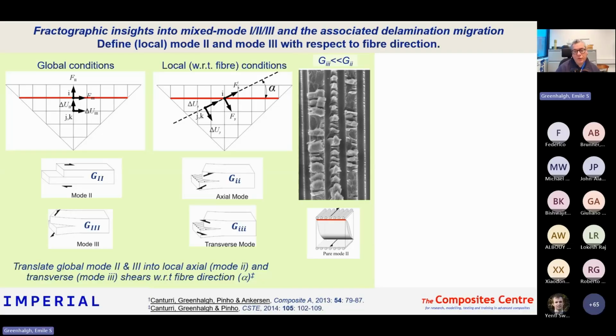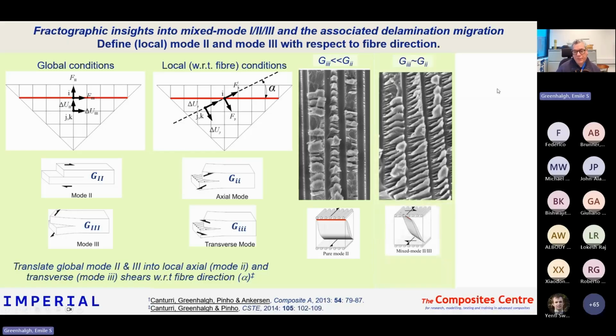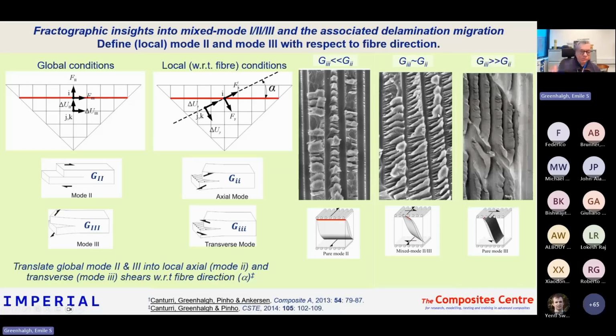So if we have a local mode 2 that dominates, then we see shear cusps which are orientated perpendicular to the fibers. These are the fiber tracks and these are the cusps. But if we start to introduce that local mode 3 component where we're trying to drive the crack in a different direction to the fibers, we start to see these cusps are twisted or rotated with respect to the fiber direction.